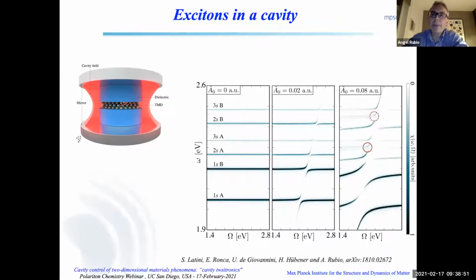The question is, what happens if you keep increasing the intensity, which is the coupling, and you go to what is a strong coupling regime? The first thing you should notice is that this splitting overlaps. This overlapping of the excitations between A and B introduces the appearance of new peaks with oscillator strength, which is not negligible. And then there is a higher splitting at the crossing point. And this oscillator strength survives even beyond the light cone.